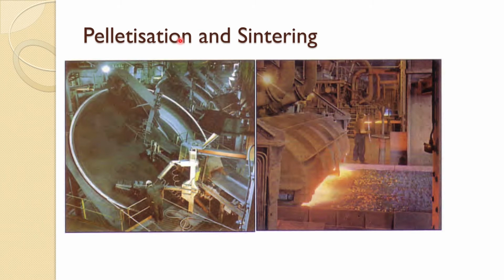So, this figure, the right one, is showing the actual sintering machine. This is the ignition hood. Once it is coming out from under the ignition hood, the first layer is already very hot and sintered, and you can see the red hot underneath of the first layer, which means the flame front has already established and is traveling down as the gas is getting sucked from the bottom. So, the flame front is moving downward across the depth, and the sinter at the top is getting cooled by the cold air.